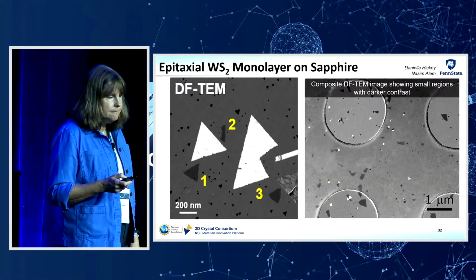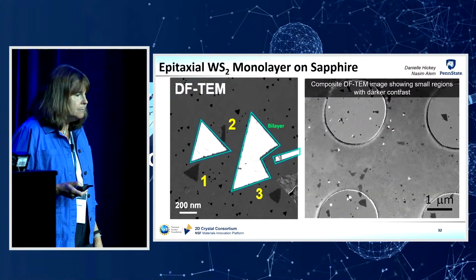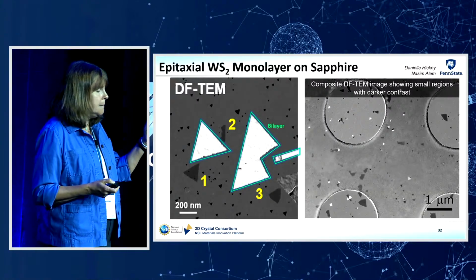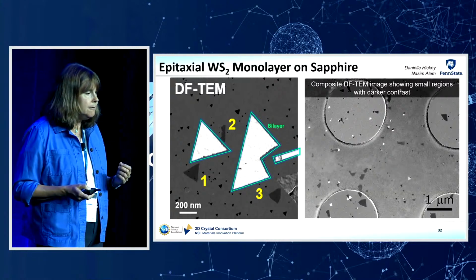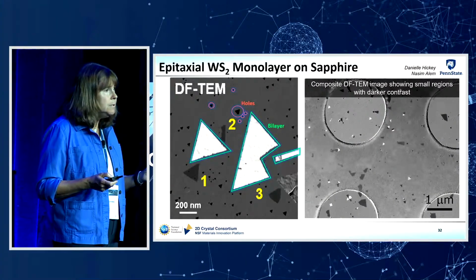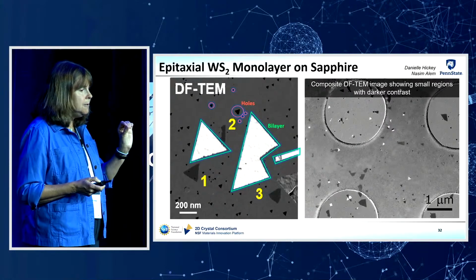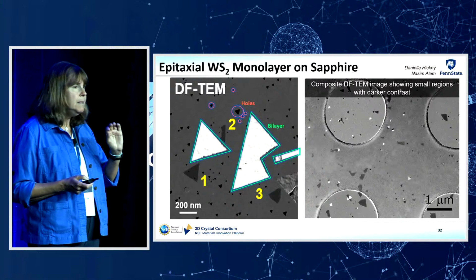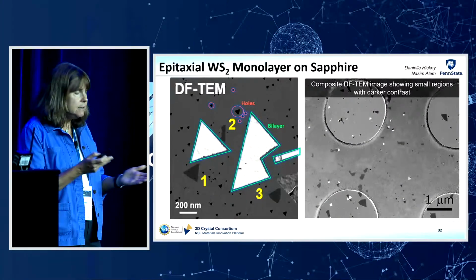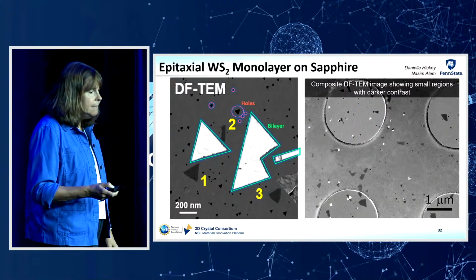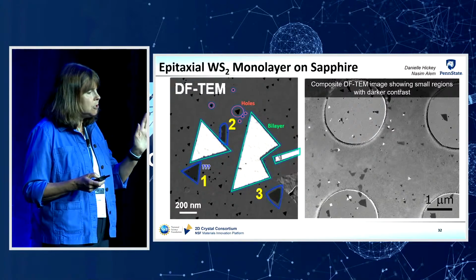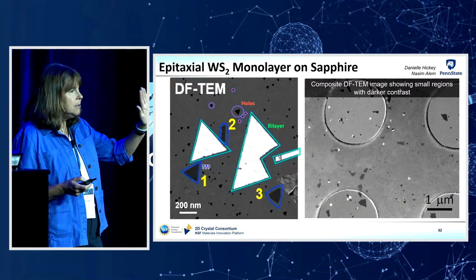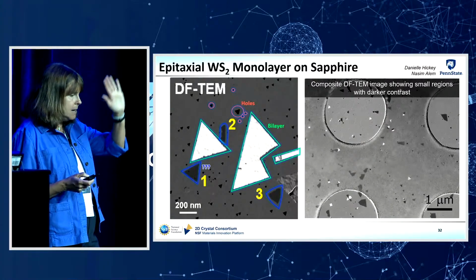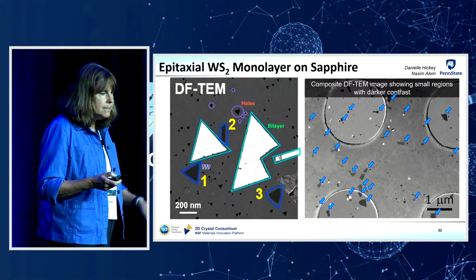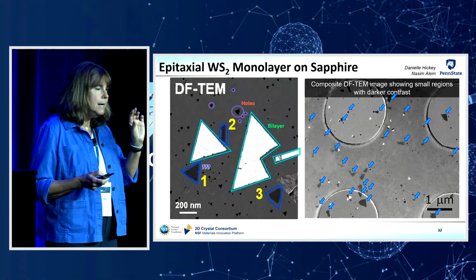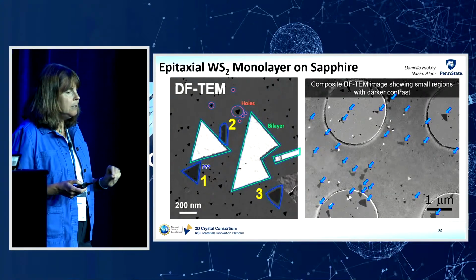So let me just point out a couple of features that are present in these monolayer films. So we have the bilayer domains that show up with a very bright contrast in the dark field image. We also have some holes in the film. So these are either regions where the film hasn't completely coalesced, or maybe they're holes that form during the transfer process as we pull the film off of the substrate. And then we have these additional features which have a darker contrast. So they're embedded in the monolayer, but they have a darker contrast than the surrounding region in the monolayer. And you can see if you look at this composite image that there are a number of these small regions that show up in the monolayer.